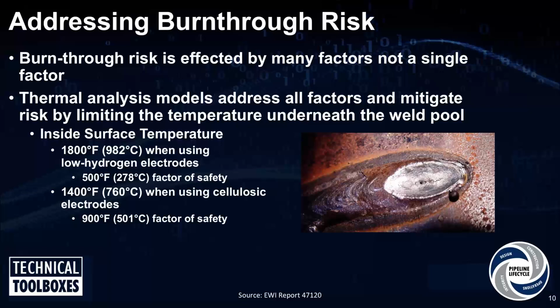What these models do is they predict what is referred to as the inside surface temperature. An inside surface temperature is the temperature directly under the weld pool, the area that was believed to get the hottest from welding at the time the weld is occurring. So if you monitor that location and you keep it below a certain limit, the belief is then you won't have a burn-through risk. And you kind of see that in the picture on the bottom right here.